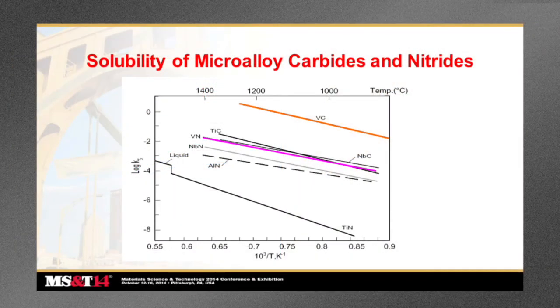Now let's talk a little bit about the solubilities, the relative solubilities of these carbide and nitride formers. This is the classic solubility curve for each of the primary microalloys: vanadium carbide, vanadium nitride, titanium carbide, titanium nitride, niobium carbide, niobium nitride, and aluminum nitride. As you can see, of all the nitride formers, the vanadium nitride is the most soluble. Niobium nitride is next, less soluble. Aluminum nitride is even less soluble for the most part than niobium, but very similar. And then you have titanium nitride that precipitates pretty much on solidification of the steel. It is extremely difficult to get back into solution.